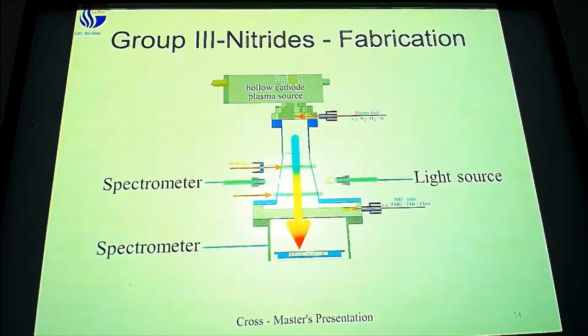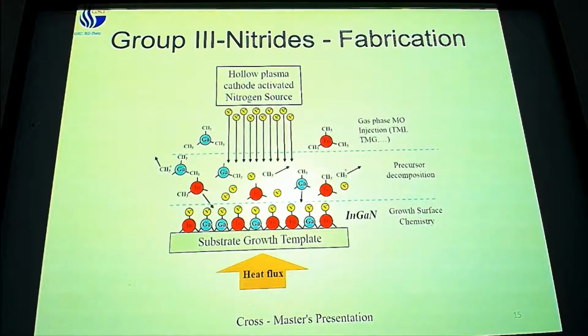For MEPA MOCVD, or Migration Enhanced Plasma Assisted MOCVD, we use a different method. Instead of having a high temperature here to get our nitrogen precursor, we use plasma. So we create a nitrogen plasma here, which is positively charged nitrogen nuclei, as well as electrons coming down. And they pass down and they combine at that surface, similarly with the gallium.